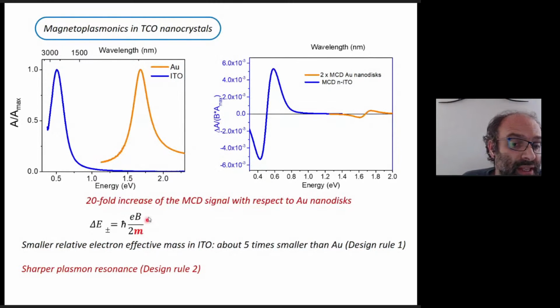This means that if you apply 1 Tesla of field to gold nanoparticles, you will have a certain shift. But if you apply the same 1 Tesla of field to ITO nanoparticles, you will have a much stronger effect because m is smaller. And this you can see here from the magneto-optical response of gold nanodiscs and indium tin oxide nanoparticles. You see that the magneto-optical signal is much bigger, and these systems are still non-magnetic. So this is a very important thing.